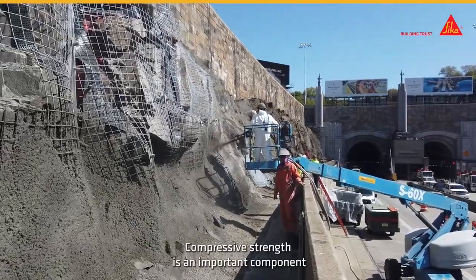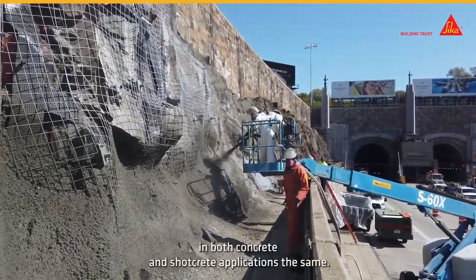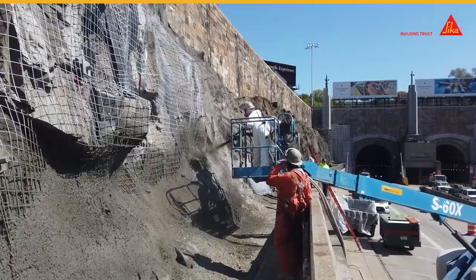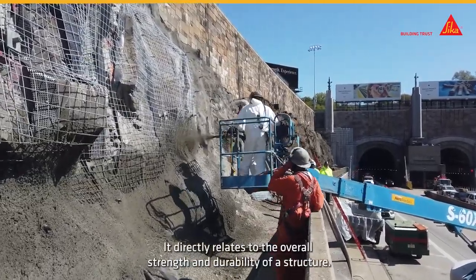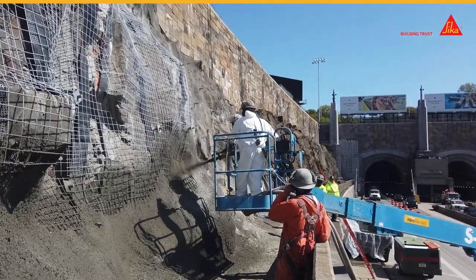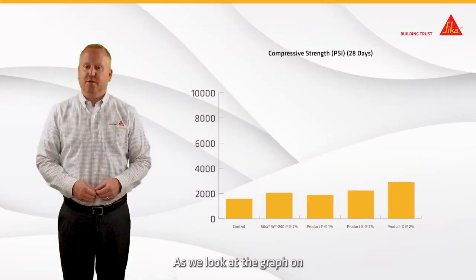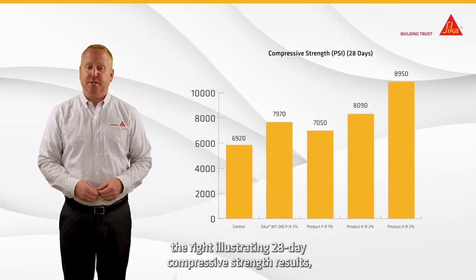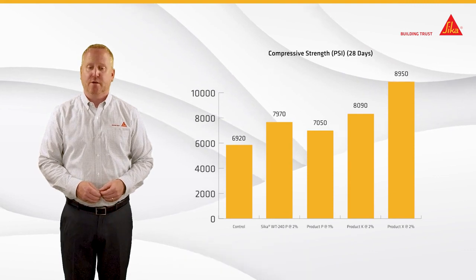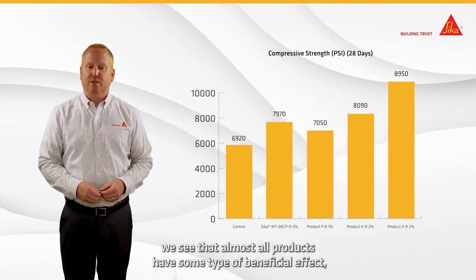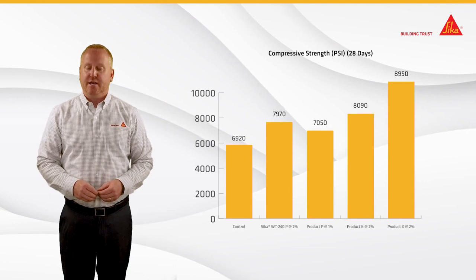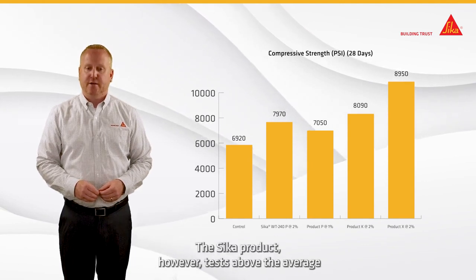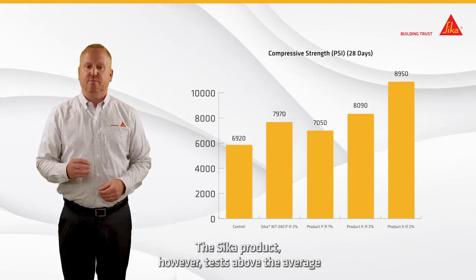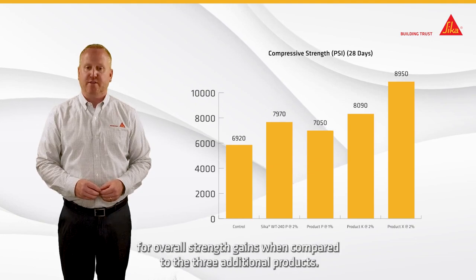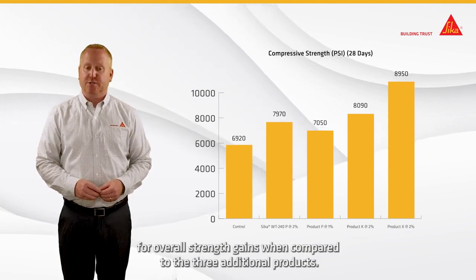Compressive strength is an important component in both concrete and shotcrete applications alike. It directly relates to the overall strength and durability of a structure. As we look at the graph on the right illustrating 28-day compressive strength results, we see that almost all products have some type of beneficial effect, increasing the compressive strength. The Sika product, however, tests above the average for overall strength gains when compared to the 3 additional products.